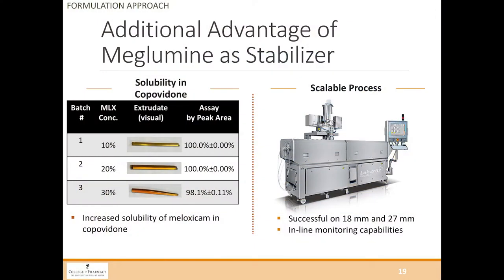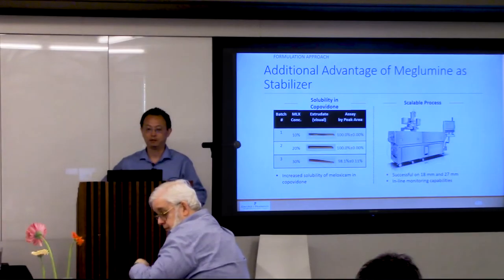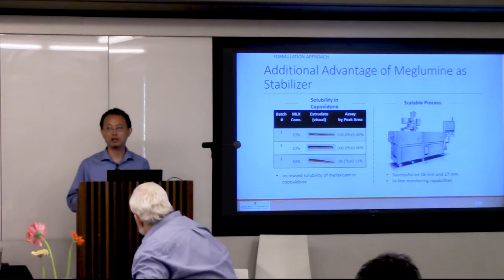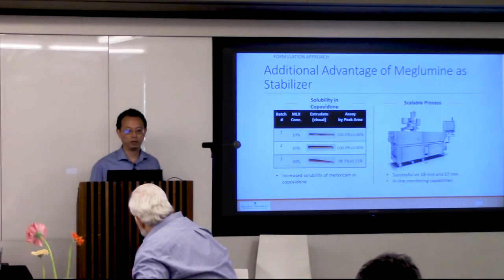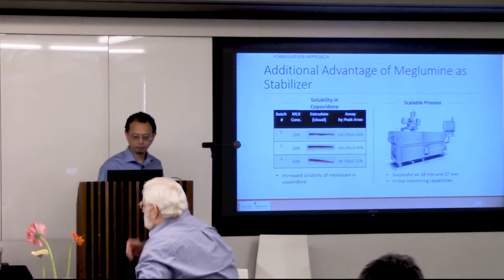Another advantage of meglumine is that once we form an in situ salt, we can actually put more meloxicam in the formulation. We can increase the drug loading up to 20%, which we can never do using meloxicam only. So the salt actually has a higher solubility in the copovidone than the meloxicam by itself.